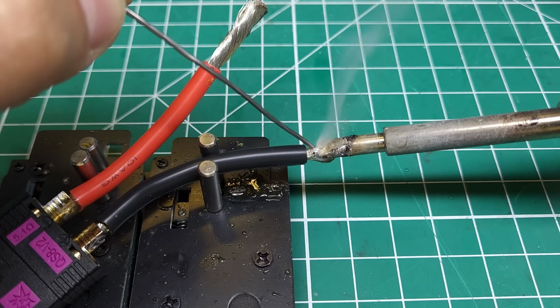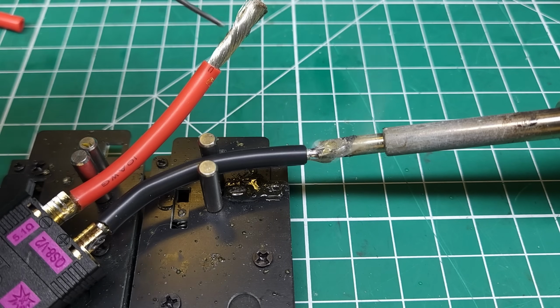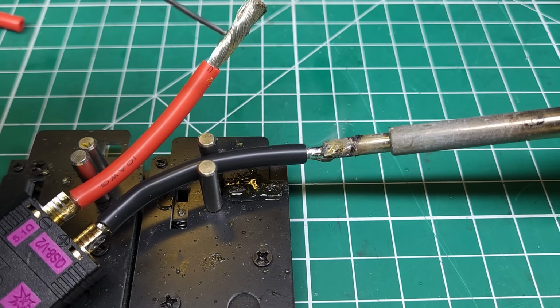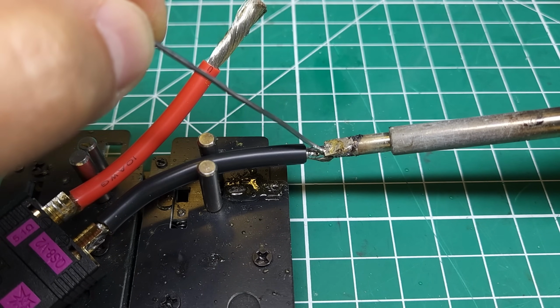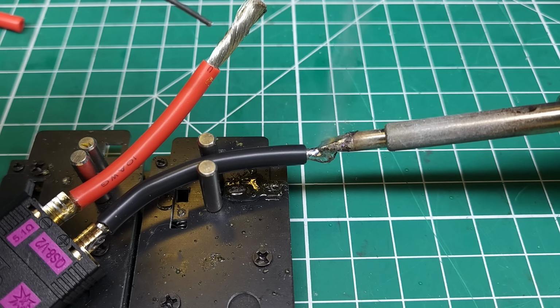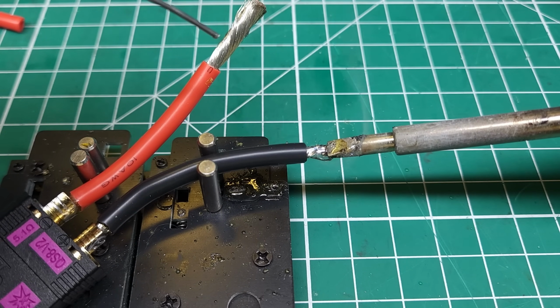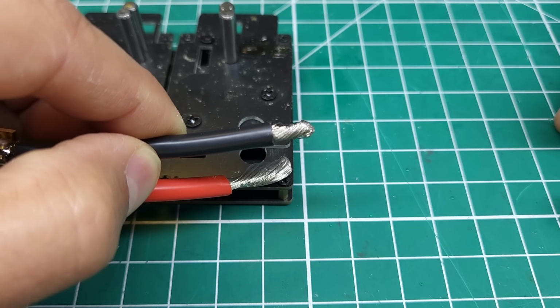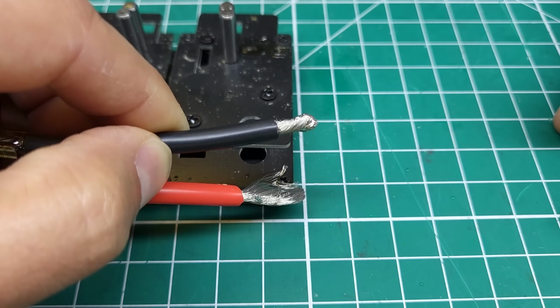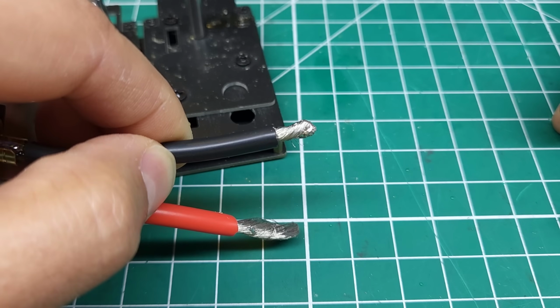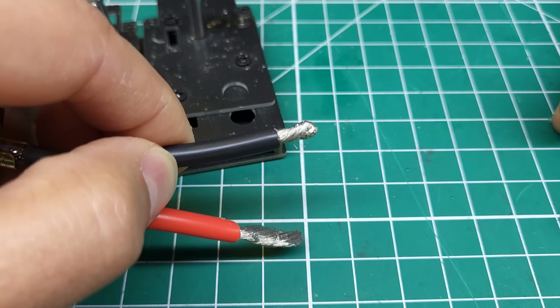As you'll see, that's going to start wetting the metal, and it looks like we're getting a nice solder connection here. We've got nice, bright, wet metal here with solder flowing into it, and that looks pretty darn good. We've got solder all over it. However, if I flip this wire over, as you can see, there is no solder on the bottom whatsoever, and it doesn't matter how long I hold the soldering iron on there, it's not going to get to the bottom.